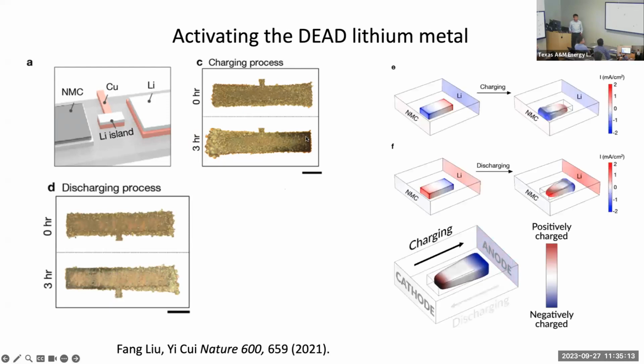So we actually simulate this process during battery charging and discharging. What happened to this isolated island? Isn't that very interesting? Even though they're not connected electrically, they're isolated, they respond to the outside current, left to right, right to left. The degree of response is easy to understand. If your external current is very high, you cause a larger voltage gradient inside the battery cell, and the response is stronger.